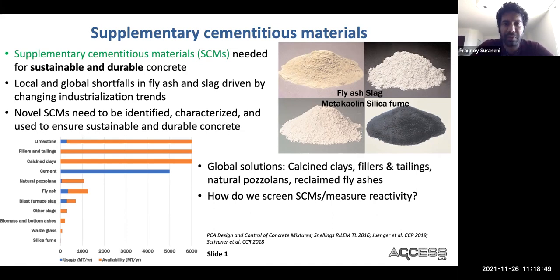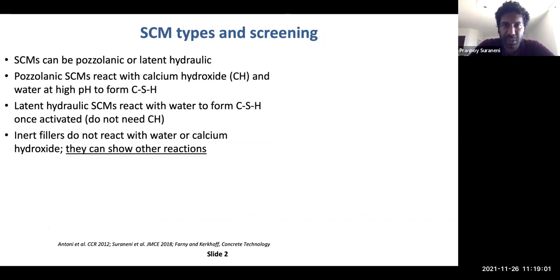Now, the biggest thing when using these supplementary cementitious materials is how we screen supplementary cementitious materials or measure their reactivity. I'll talk a little bit about what I mean when I say screen or reactivity. So supplementary cementitious materials, essentially, are either pozzolanic or latent hydraulic. Pozzolanic materials are ones which react with calcium hydroxide and water at high pH to form CSH. On the other hand, latent hydraulic SCMs do not need calcium hydroxide. They react with water to form CSH, as long as they are activated, which could be through pH, through fineness, or through other chemical means.